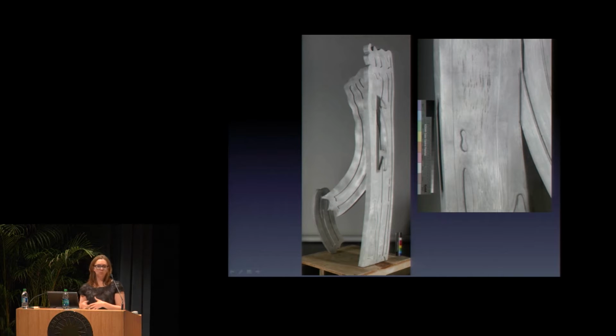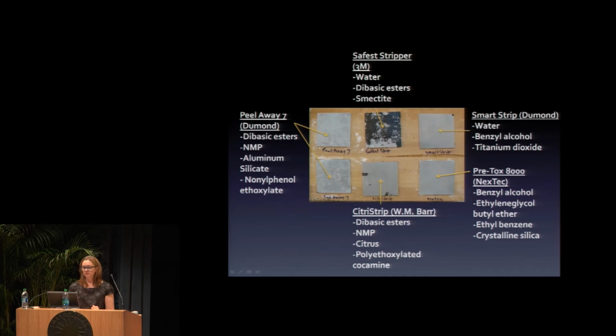So at the time, we did do some steam cleaning to clean it. If I were to do it again, I would have gone back in with carbon dioxide blasting, because in retrospect, probably introducing the water to the surface was not the best surface prep prior to cleaning. But we did test several different paint strippers, and I did want to briefly mention that using chemical strippers in combination with carbon dioxide is one possibility. I know it's not eliminating the VOC, but for this particular object that had such thick epoxy and polyurethane layers, it felt necessary to me.